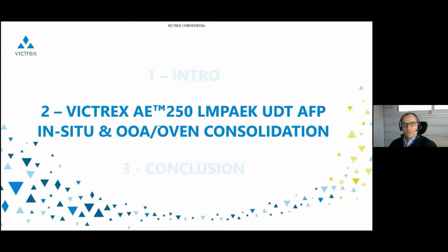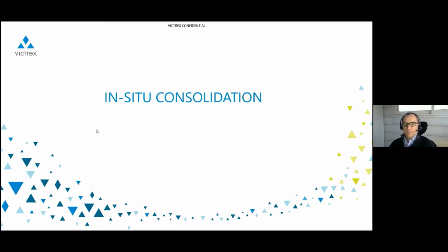So now I want to move on to the main section of this presentation, which is about the processing of the UD tape for in-situ and out-of-autoclave application. And then you will see how we achieve high speed close to thermoset. To do so, I wanted to give some more background and also focus on some studies we've been managing at Victrex with partners, dividing them into two sections. One is in situ, so there's no post-consolidation. You lay up the tape and the part is done. And then the next part will be about out-of-autoclave, where you have a post-processing consolidation step.